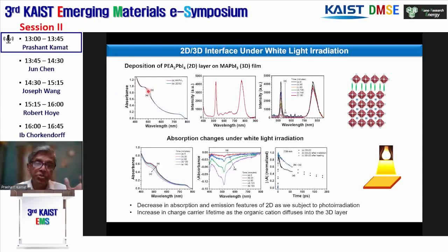You can see here, if you take an absorption spectrum, there is a 2D phase that's coming in here. And then when you shine the light, this decreases. This is the emission spectrum of the same 2D-3D film. They are characteristically separated. There is no energy transfer in this case. We see a characteristic peak of 3D and 2D. But when you shine the light for about 3 hours, the 2D peak totally disappears. There is a small change in the 3D, maybe because of movement of these cations, and there is a small blue shift too.